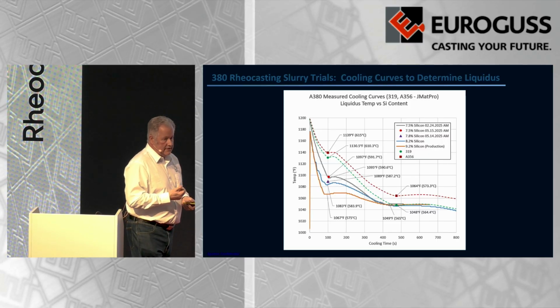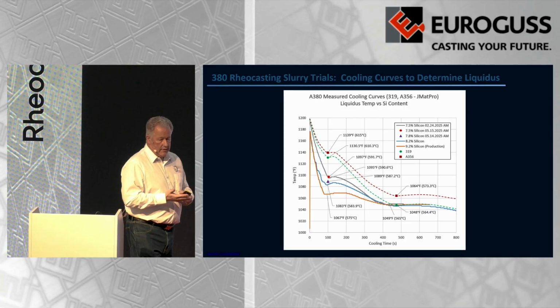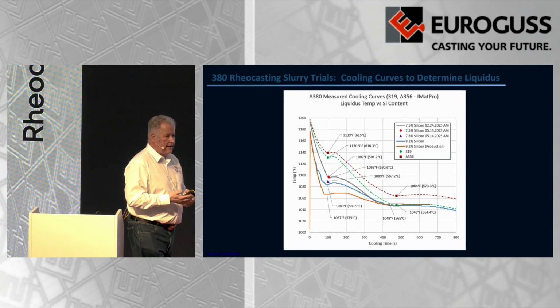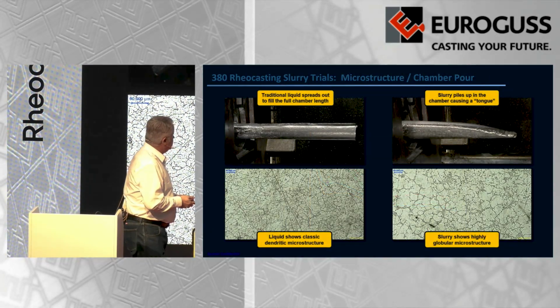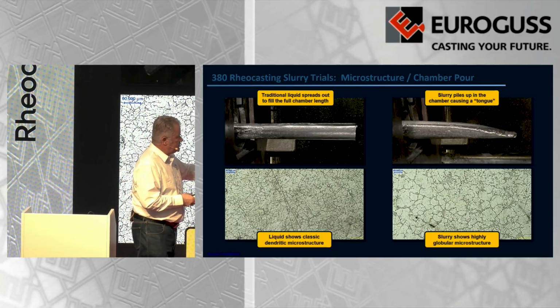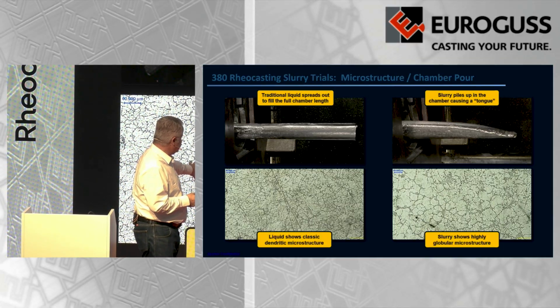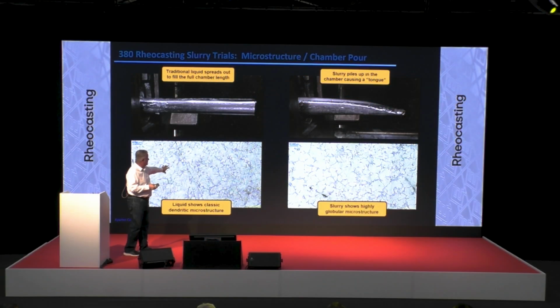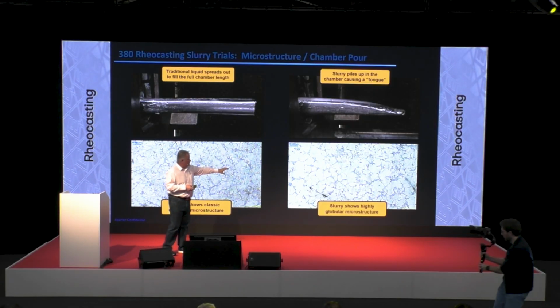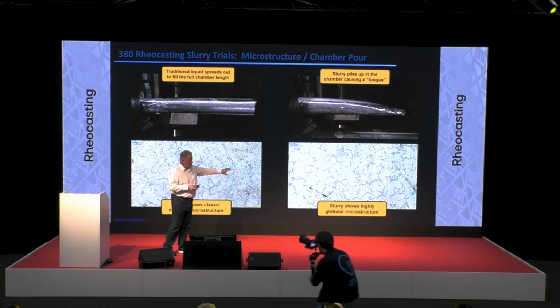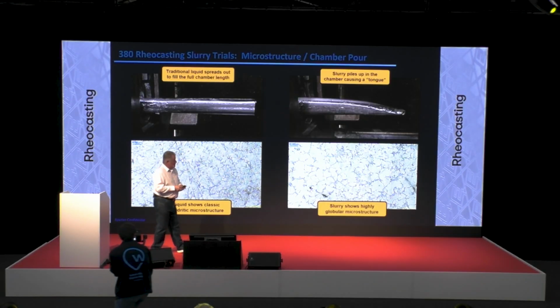We've been doing trials in terms of traditional powertrain alloys. I'm using US names for them, but we can't use A383, the silicon content is too high, and that is too close to the eutectic point. But we've been using A380 and A319. So you can see here a couple of images of the grain structures: a traditional dendritic structure in an A380 alloy, and over on the right-hand side, the globular microstructure that you have in the Rheocast alloy.